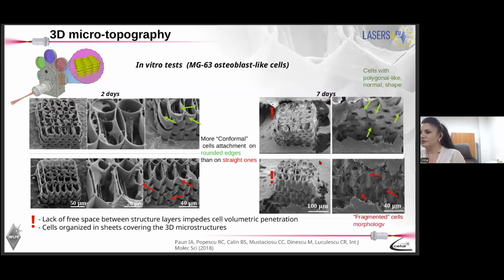We have a first bad result, which actually we expected. The cells mostly attach on the outer side of the structure, and they were struggling to get inside, but with less success because there is no room inside the structure because the layers are too close to one another. We have another conclusion here, maybe not so useful at this point, but maybe later, because the cells, as you can see here, have more round edges than sharp ones.